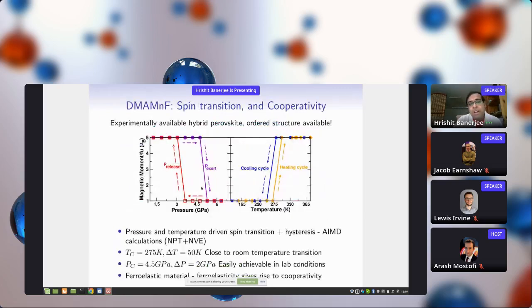And we find that in this material as well, we can show a pressure-driven spin crossover and a spin transition with a reasonably large hysteresis width of 2 gigapascals with a Pc of 4.5 gigapascals. And when we do ab initio molecular dynamics calculations with both NPT and NVE combination, and calculate the temperatures at which these changes take place, we can show that we have a Tc of 275 Kelvin, which is very close to room temperature, and a delta T of 50 Kelvin, which is a reasonably large width of hysteresis. So this material is also ferroelastic, and the ferroelasticity gives rise to the very large cooperativity, and magnetic interaction helps in that.